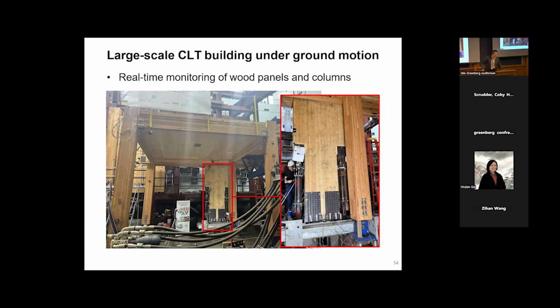This panel is a self-centering panel. You don't see it, but there are post-tension pre-stressed tendons in the middle. And our purpose was to utilize this distributed sensor technology to measure the detailed strain distributions within the different wood panels. As you can see, there are many pieces. This panel was composed of many pieces of wood. And we found that different pieces have different strains because the load was not uniformly applied to all the pieces.